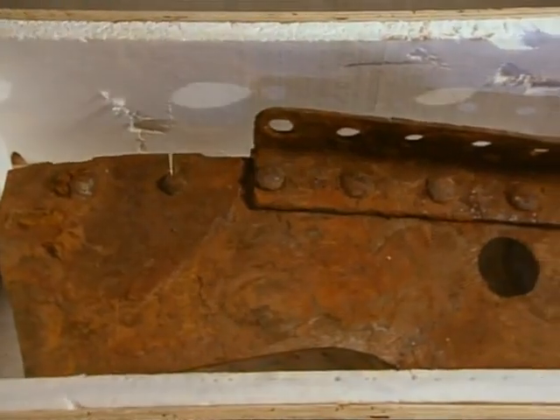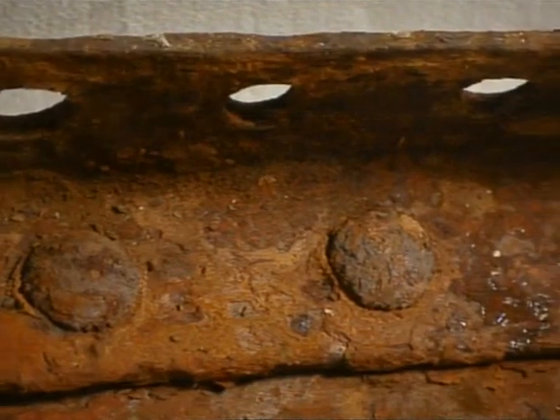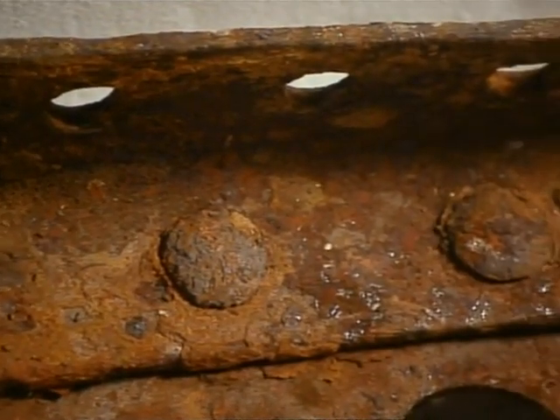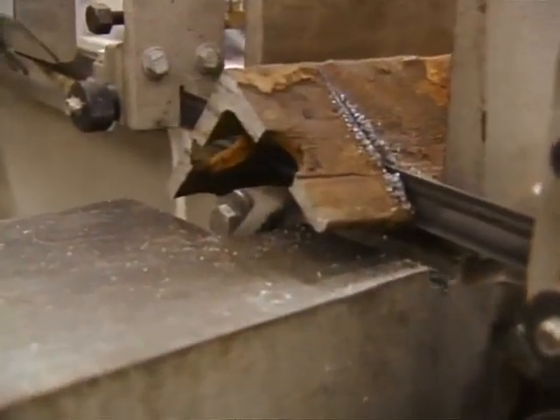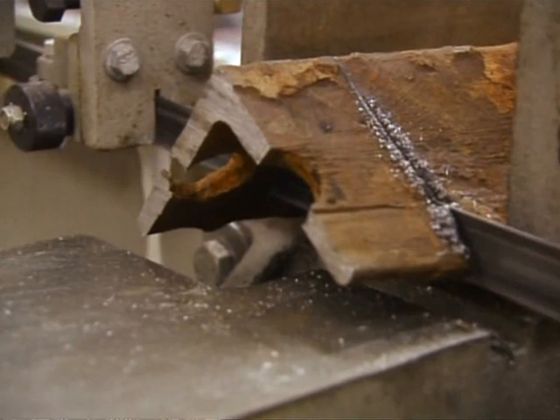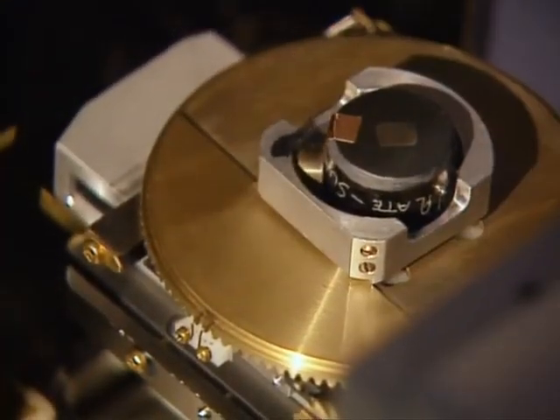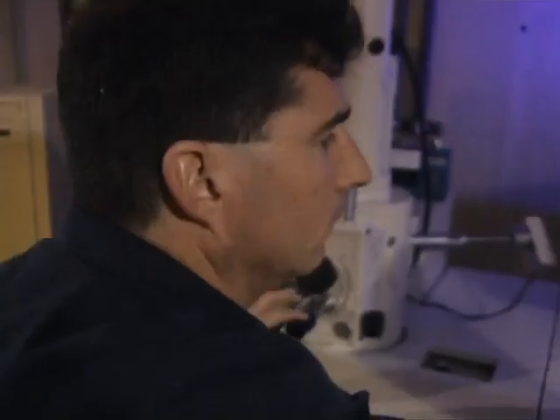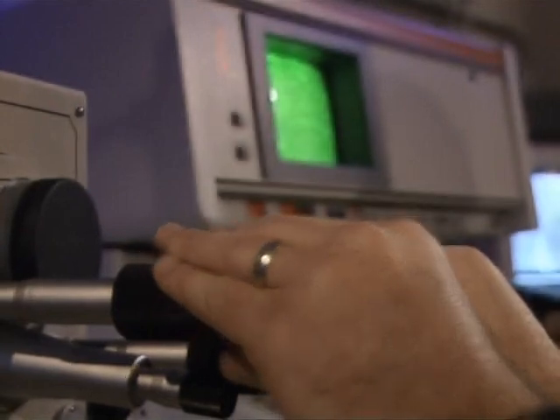Under the guidance of metallurgist Professor H.P. Leighly, a team will test to see if Titanic steel is especially brittle. A small sample is cut and loaded into a scanning electron microscope. Metallurgists Chris Ramsey and Scott Miller peer deep into the steel's microstructure. Pearlite, lots of inclusions. Let's focus it real fast, and then go back down in magnification, see what we have. They are looking for potential weaknesses and defects in the steel.